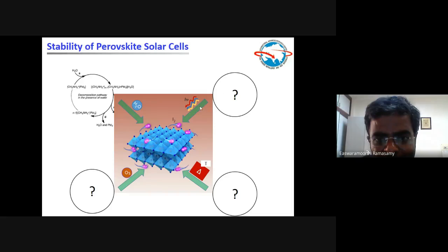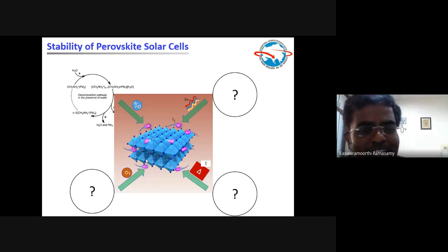When light interacts, it also degrades. Heat also affects the quality of the perovskite, and oxygen also reacts with the perovskite. So you see that perovskite is an excellent material for solar cells, but it's not very good under the light, under the temperature, in oxygen and under moisture.